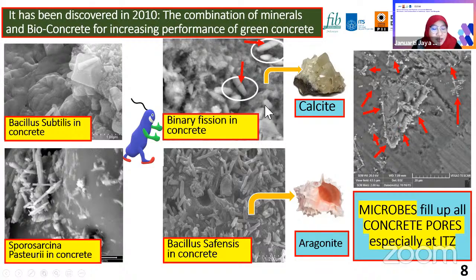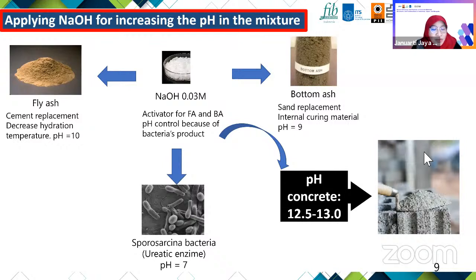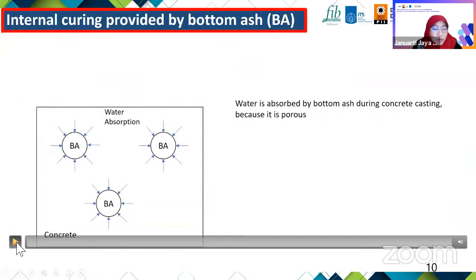We have also another innovation on using sodium hydroxide to increase the pH of concrete. So usually cement contributes to pH at 12.5 to 13 in concrete mixtures during the casting. By using fly ash and bottom ash, and bacteria may decrease the pH in concrete. So we use a very low concentration of sodium hydroxide of 0.03 molar to be introduced during the casting, and also as the water substitution. And it also increased the reactivity of fly ash.